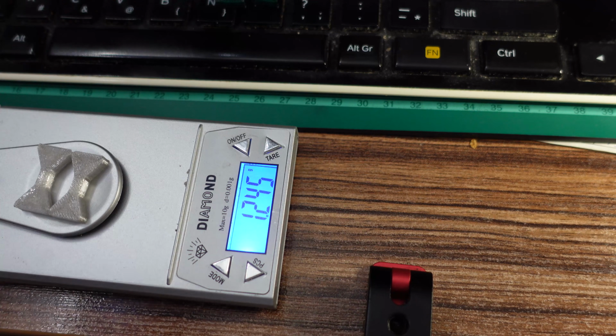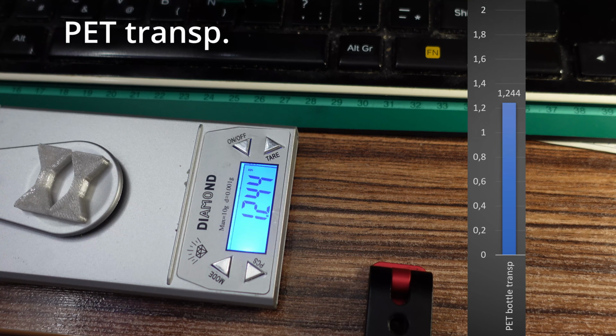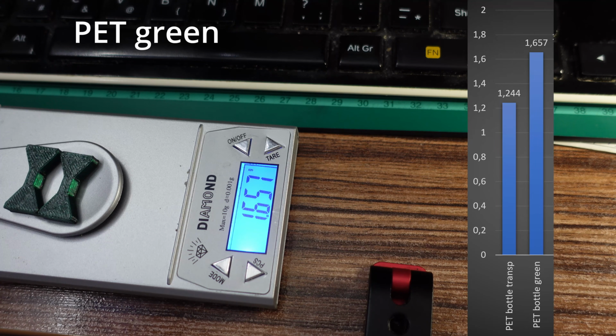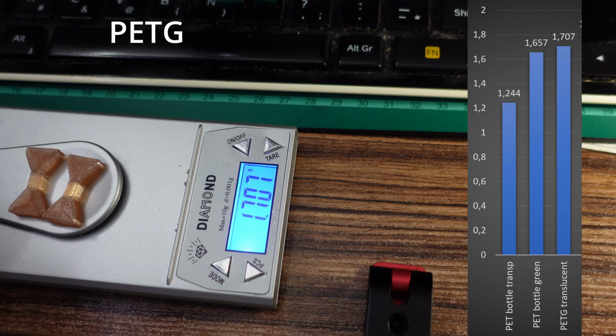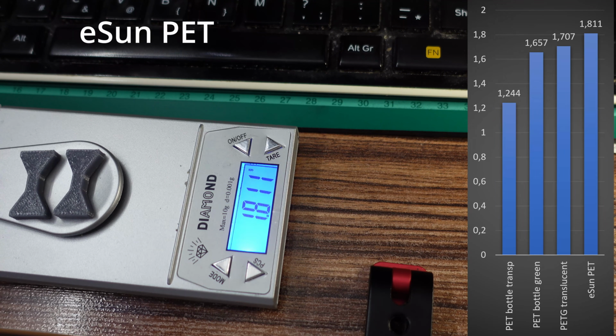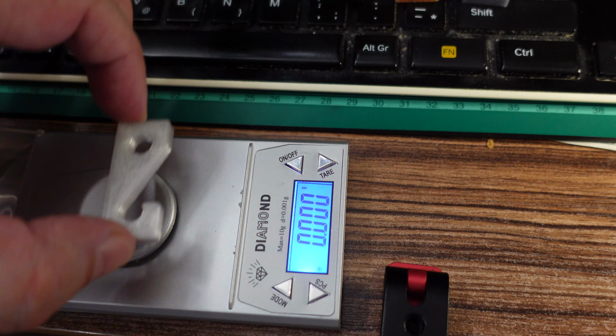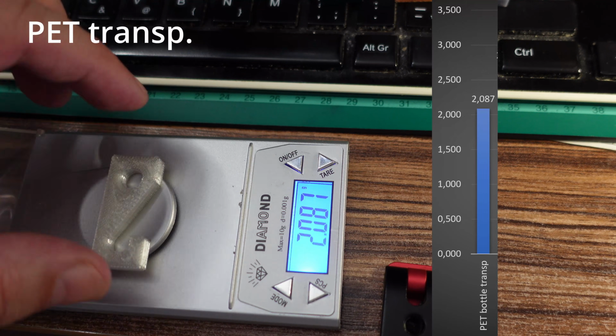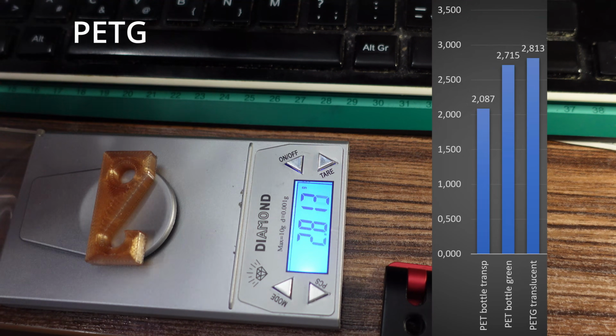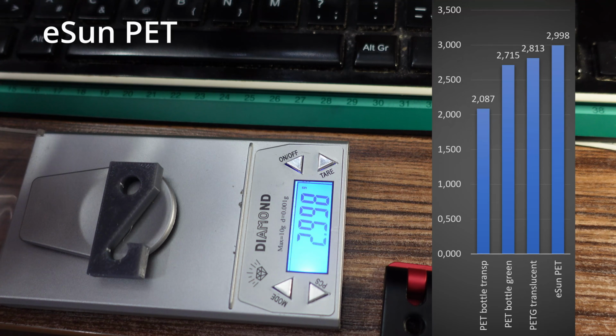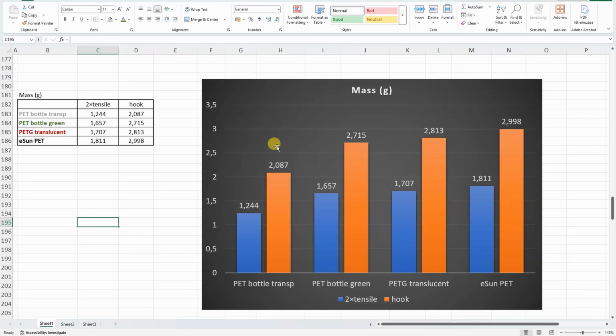Quickly to check the weight. 1.244. 1.657. Heavier. 1.707. 1.811. Let's quickly measure the hooks. 2.087, 2.715, 2.813, 2.998. It's quite obvious that there is some underextrusion with the transparent PET because it's much lighter compared to the green version, but this is light too compared to the PETG because the density of the PET is much bigger compared to the PETG, so I believe that this is underextruded too, and this will be visible on the tests too.